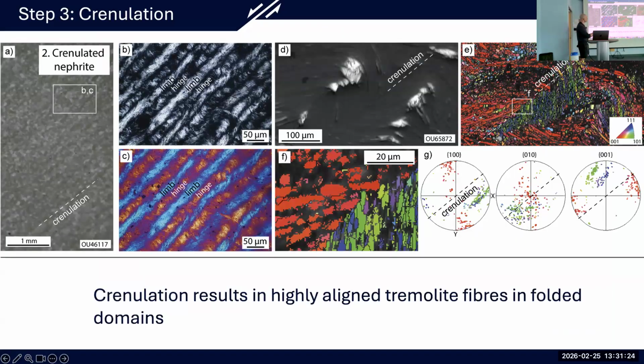So here we have those same images, and if we look at the scanning electron image, it's a bit difficult here, it's a bit dim, but you can actually see these microfolds that are occurring across these domains. Crystallographically speaking, if we look at our EBSD maps, within a given domain, we have a very strong alignment, but now things are getting a little tight, things are getting compressed, and we actually have changes in crystal alignment that are occurring on quite a fine scale. So we're beginning to develop that nephritic fabric. This deformation is still favoring very small needles as needles reorganize and regrow through this deformation. And that crenulation is giving us different orientations.